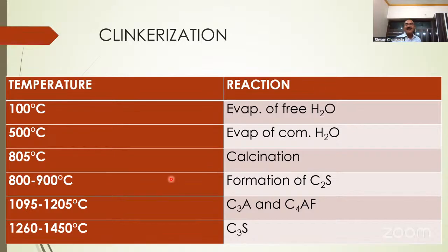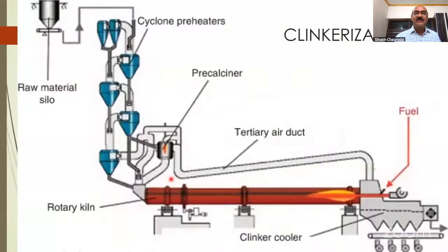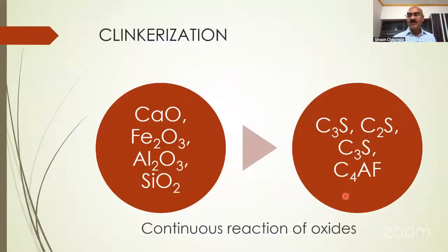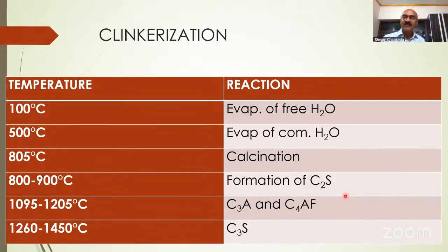That's tricalcium silicate, also called alite. That combination reaction takes place at the highest temperature, which is available here where the flame is. The rest of the reactions are completed in this particular kiln, but the last reaction takes place here. It requires around 1400 degrees centigrade to convert this tricalcium silicate.